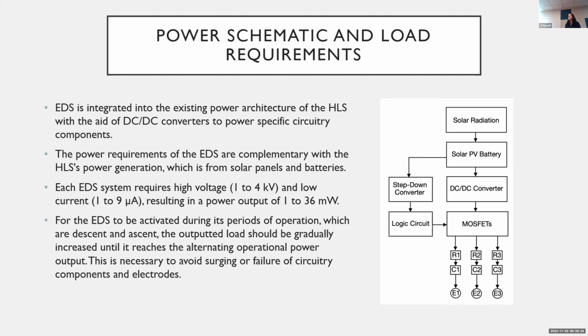The power requirements of the EDS are from 1 to 36 milliwatts. This is based on the alternating voltage and current requirements of the EDS system. For the load profile of the EDS during the period of operation, which is descent and ascent, there is an alternating sinusoid with an amplitude of 18.5 milliwatts. This is necessary to avoid surging or failure of circuitry components.